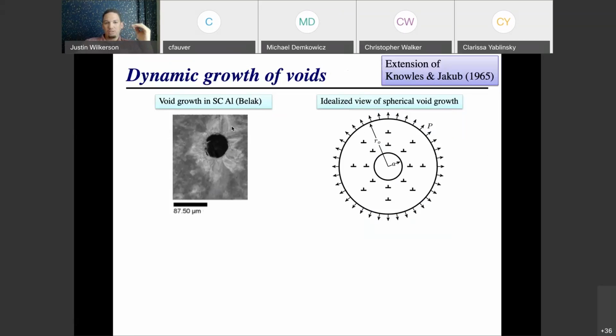Okay, so if I want to grow a void very fast, I have to drive dislocations to move at very fast rates, right? But they're limited at how fast they can move. They can't move any faster than the shear wave speed. So that's going to put an upper limit on how fast voids can grow.